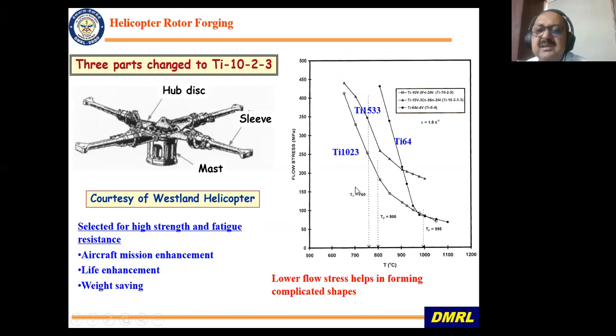Why 1023 is very attractive is because it has got one of the lowest flow stresses. Here I'm plotting flow stress versus temperature, and it has got one of the lowest flow stresses, and so it can reproduce the die cavity very well, and that is why 1023 is very widely used for closed die forging applications, even much better than Ti64 and other alloys, which have got very high flow stresses.